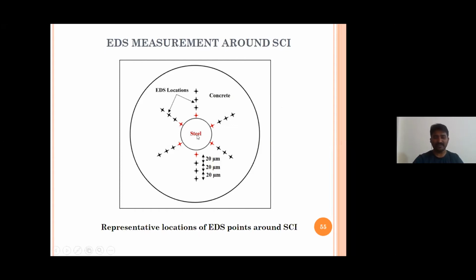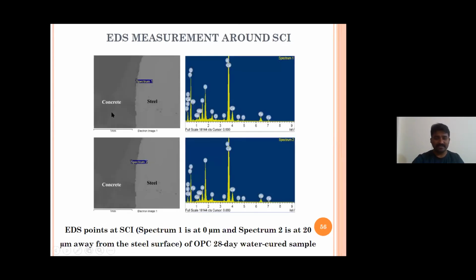To identify what kind of hydration product is formed at the interface, we have used energy dispersive spectroscopy, what we call EDS analysis. Okay, so this is my steel and this is the interface of the steel. The red portion as you are seeing is at 0 micrometers, very close to my steel surface, and I have started taking points 20 micrometers away from the steel surface. This is how it looks. For example, this is my steel surface and this is my concrete part. Very close to my steel surface, I have selected one point, and at that point you will see the chemical properties, right? What kind of ions are there? Calcium, silicon, aluminium, iron, oxygen and all.